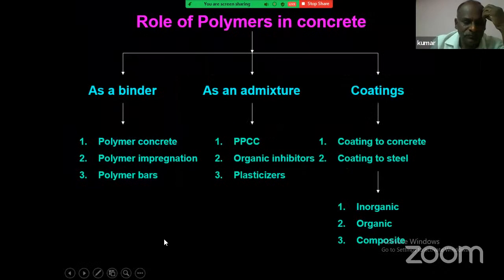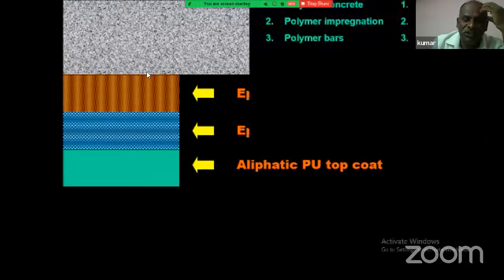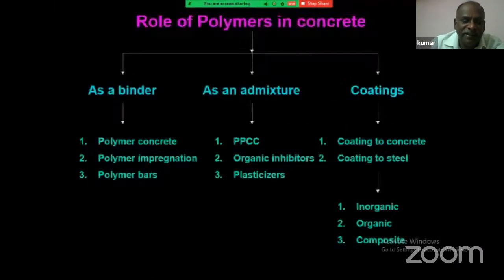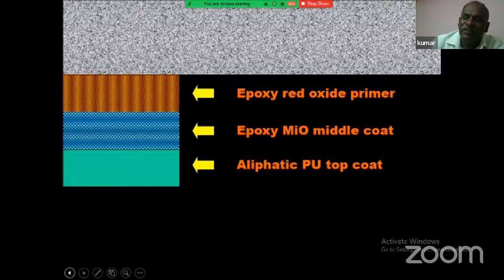Okay, now we can see how this is getting protected. For example, this is epoxy red oxide primer. It has very good adhesion. Then epoxy MIO, you are seeing here in close-up, is a flaky type of pigment. The flaky type means that chloride cannot travel straight; it will have a long route to move. Because of that, MIO is added into epoxy. Finally, the aliphatic PU top coat is given. The PU top coat is resistant to ultraviolet. So this is the mechanism.